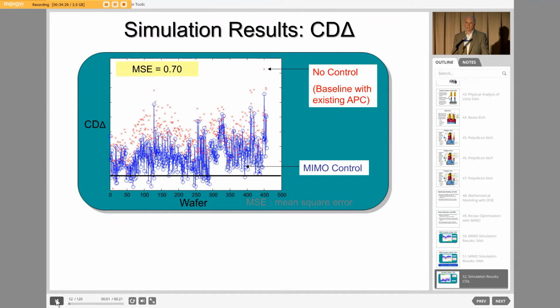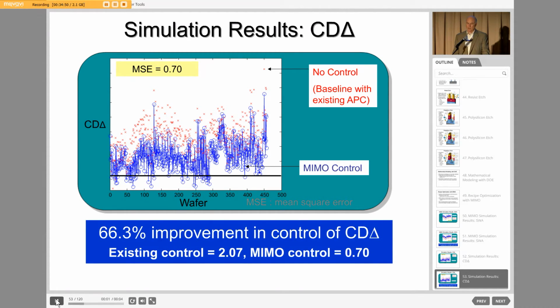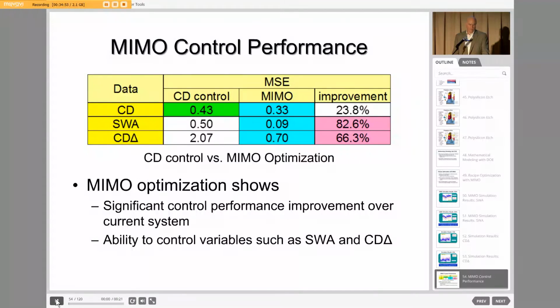The CD delta is, again, the difference between the CD at two spots on the wafer, one near the center of the wafer, one at the edge of the wafer. And again, you can see with MIMO control, we can do a much better job of staying close to the target. And the red X's are where we don't control for that, and you can see it works very poorly. So again, this demonstrates the value of APC. And then the summary table here is just to show you some of the percentage improvements, which are quite significant, quite motivating. We basically worked on this project and then it was handed back to the vendor and IBM, who then didn't tell us what they did after that point, but it was clear that they were going to work on it.